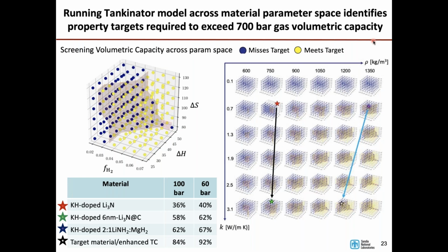And similarly, if you were to put that into the 6 nanometer porous carbon, you make a huge improvement in the thermal conductivity, but you're still not where you need to be in terms of the loading, and really more specifically, it's the thermodynamics that are limiting things here. Alternatively, if you look at this 2-to-1 lithium magnesium material that we're focusing on now, you can see we've been able to get a much higher usable capacity out of that.